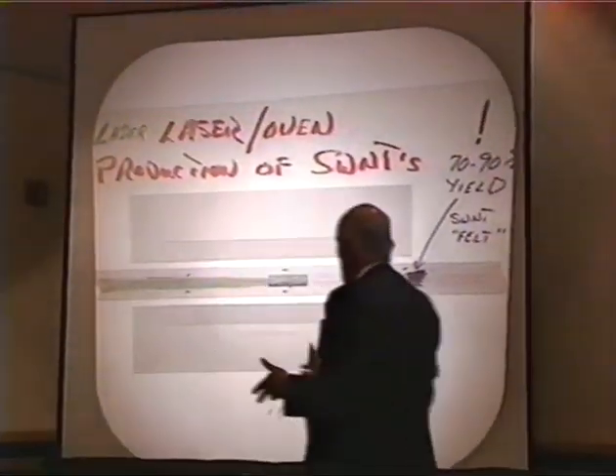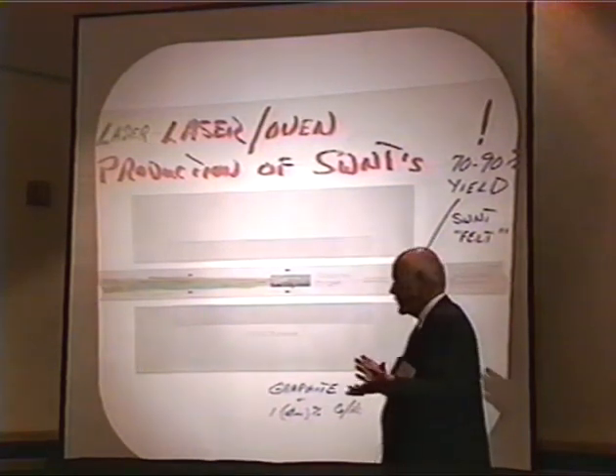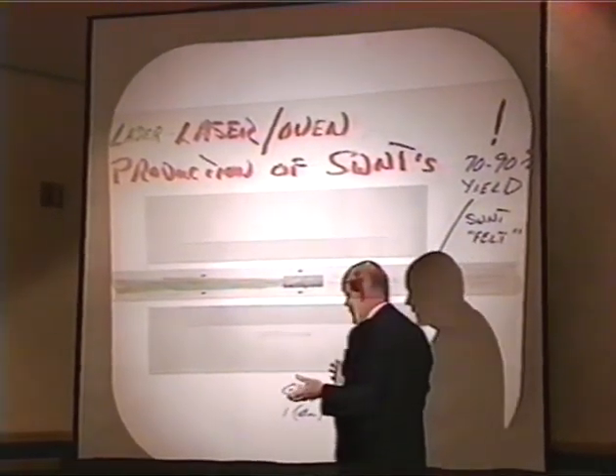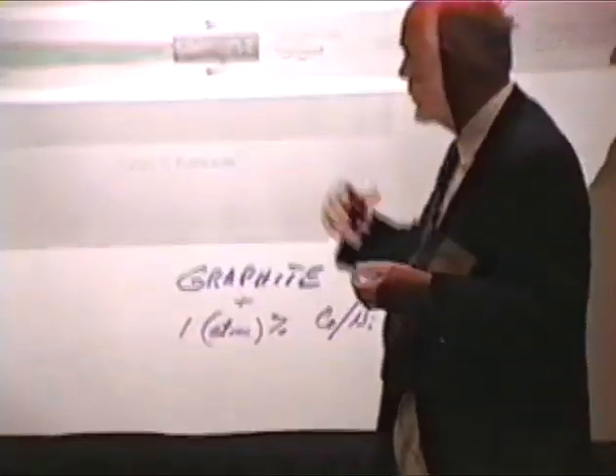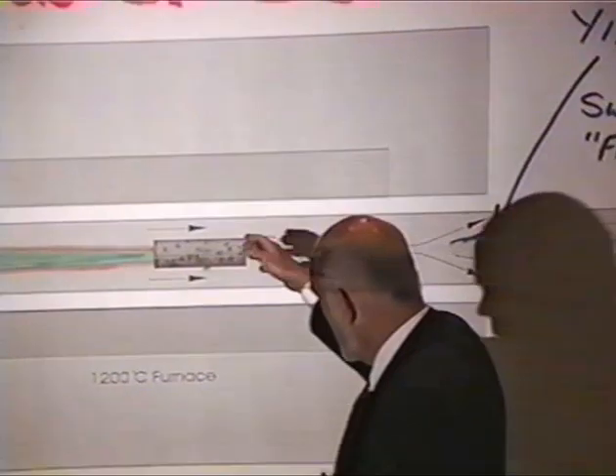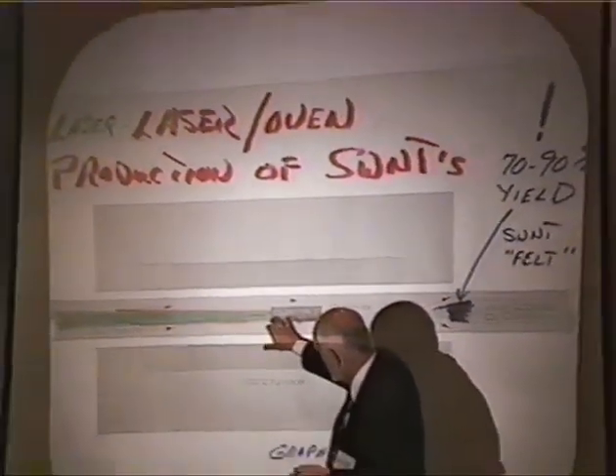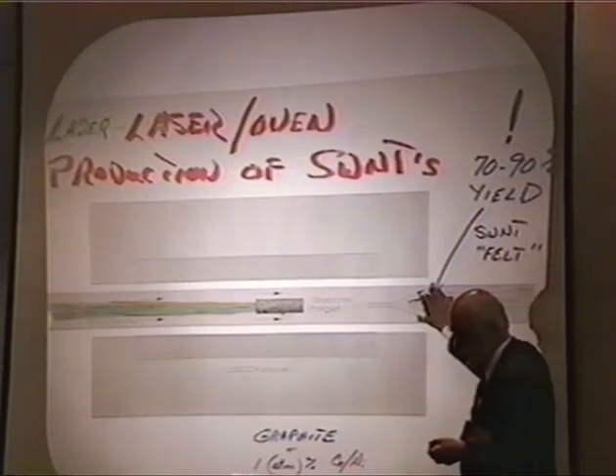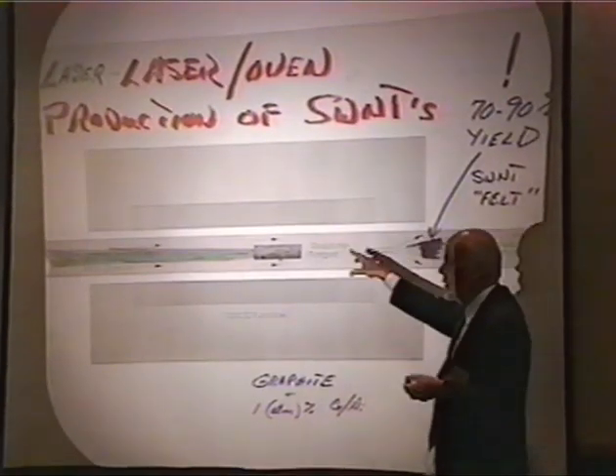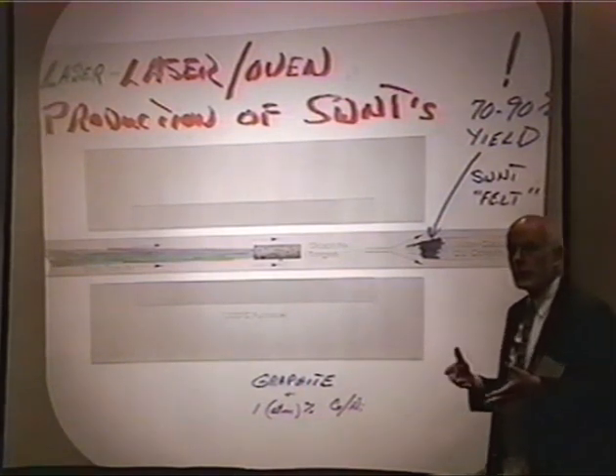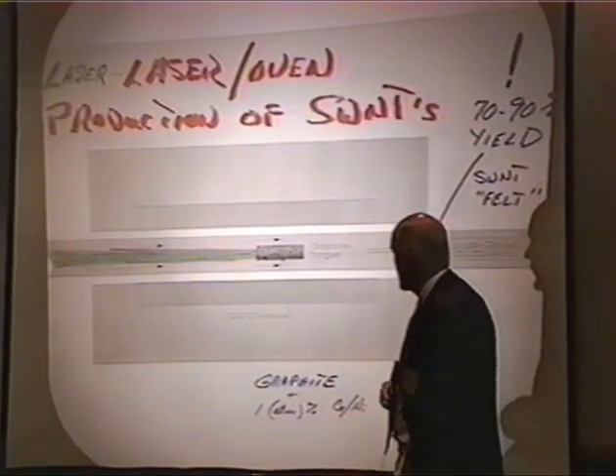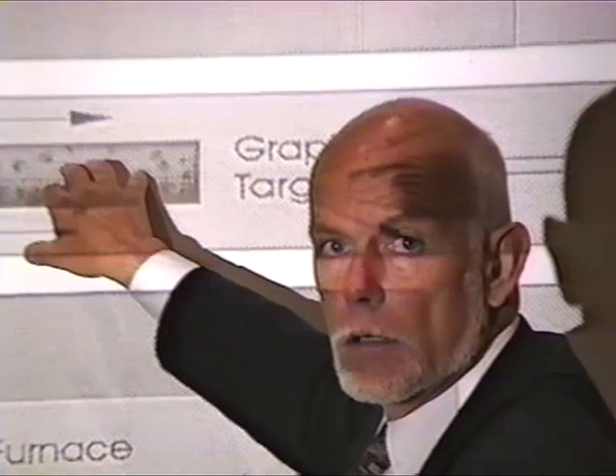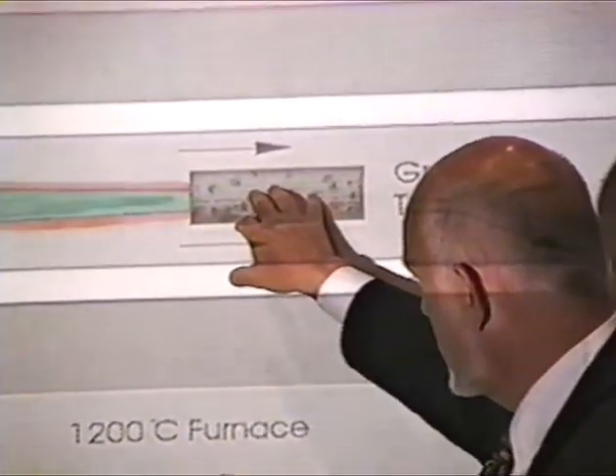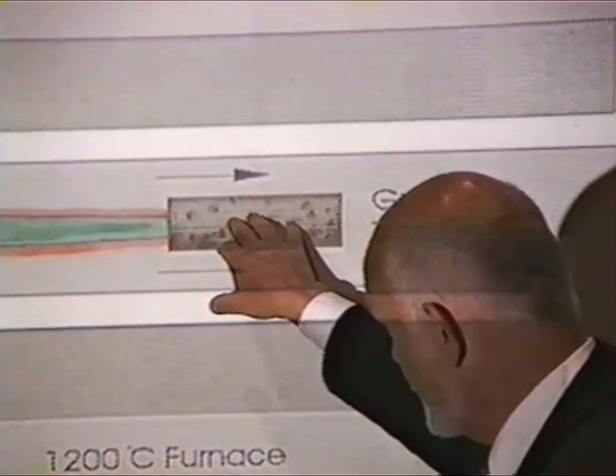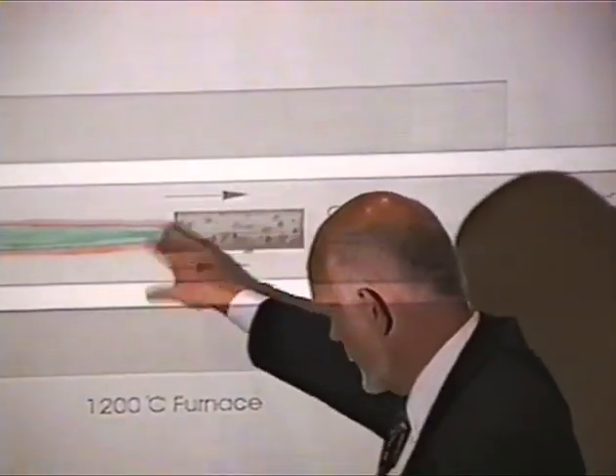We got into this game a while back trying to figure out what the mechanism for the growth of that was, and it occurred to me that the mechanism might have a lot to do with the way the buckyballs are made. So we went into an environment which, if you just have a pure carbon target and you hit it with a laser, you collect the material that forms back here, you find that 30 to 40% of all the carbon that's vaporized condenses to form C60 and the other small spheroidal fullerenes. And we mixed in some cobalt, and by this time it was known that alloys are good for these catalysts. Cobalt and nickel catalyst within the carbon pressed pellet, and then at 1200 degrees vaporized this with lasers.